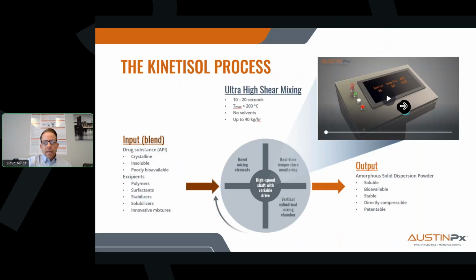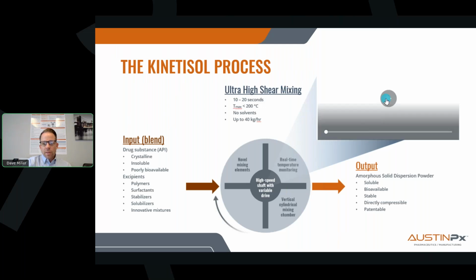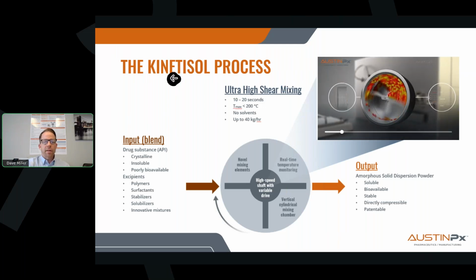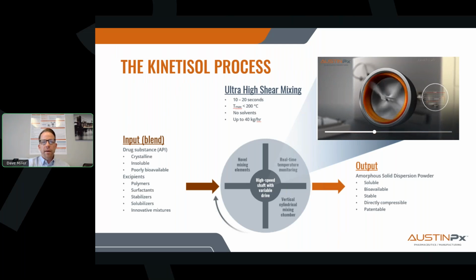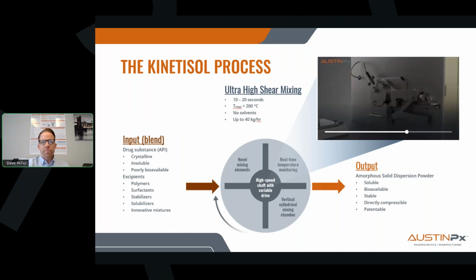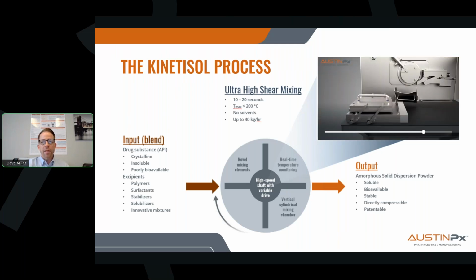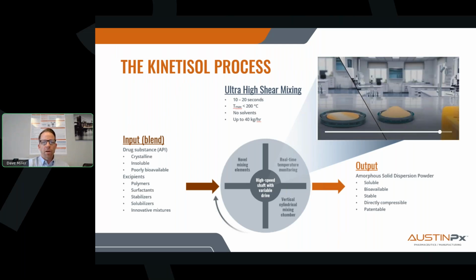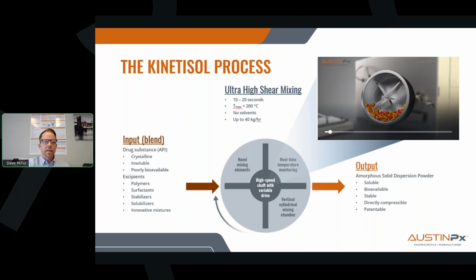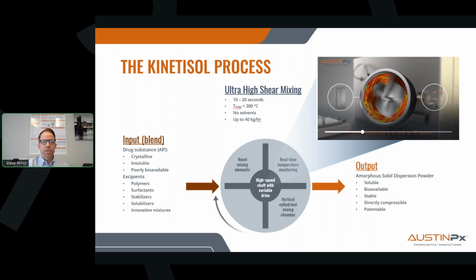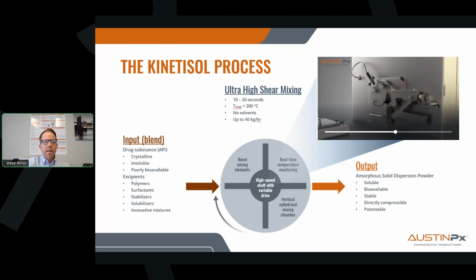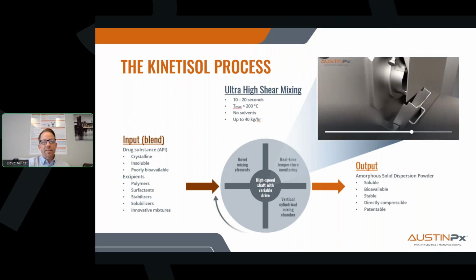Mechanically, I have a video here that you can all watch while I talk through this slide. KinetiSol operates very, very differently from either spray drying or extrusion. The solid blend of drug and matrix excipients is charged into the high-speed mixing chamber. As the blades rotate, they generate first friction in the powder bed and then shear that raises the temperature of the mass just enough to form a homogeneous melt and dissolve the crystalline drug substance. Once the dispersion is complete, the material is ejected and rapidly quenched, locking in the amorphous structure and forming an amorphous disc that you can see depicted in this video in just a moment. The entire process typically takes only 20 seconds from start to finish.